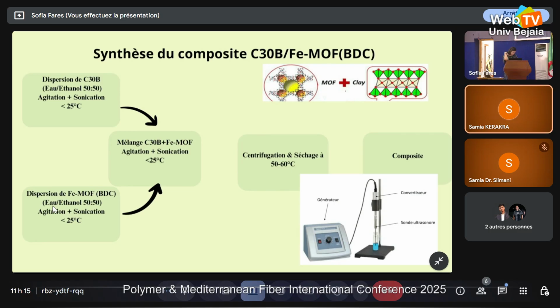Synthesis of the composites, MOF and clay. This protocol ensures good dispersion and possible physical-chemical interaction between the two fillers, even without coupling agents. So first, we disperse the clay in a water and ethanol mixture, stirred and sonicated below 25 degrees Celsius. Also, the MOF is dispersed similarly, at the same temperature and under the same conditions.